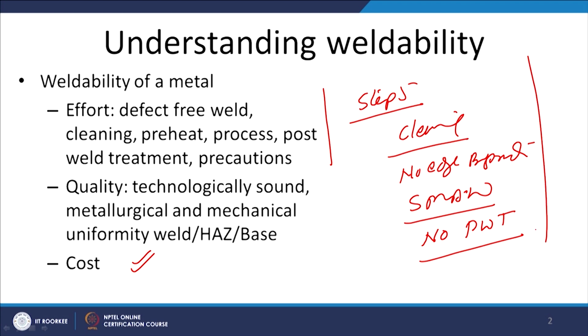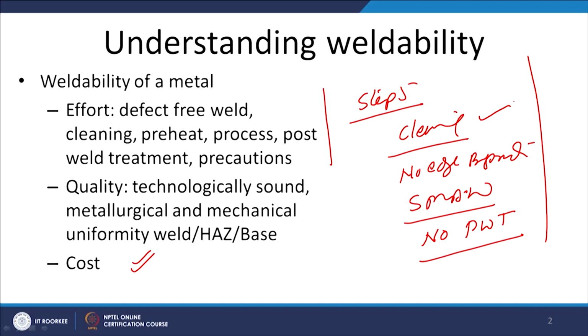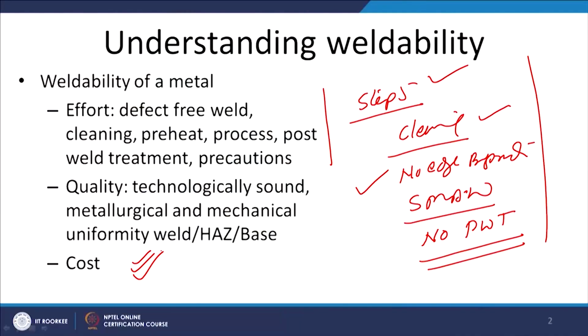Probably this will be leading to the minimum possible cost of the weld joint, but all the metals do not offer such a luxury. We may require mechanical plus chemical cleaning, we may require very precise edge preparation using J or U groove geometries, we may require laser welding or gas tungsten arc welding processes, we may require a number of post weld heat treatments, so that the required set of technological properties in joints can be achieved, so that it can really perform the required function during the service. So, the greater the number of steps required for developing a joint with the required set of properties which can perform the intended function, the greater will be the cost, and which in turn will be reducing the weldability of the metals.